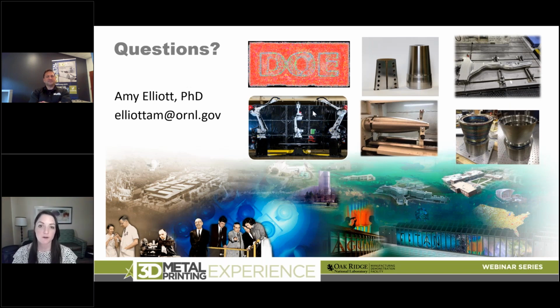Yeah, we do a lot of our IP around materials development for binder jet. So like that boron carbide aluminum system, we have a few patents around that. Collimators, 3D printed collimators using binder jet is one of our patents. We also have a few binder patents, so we custom tailor the polymer and the solvent and everything in the binder system. We custom tailor it to different materials.